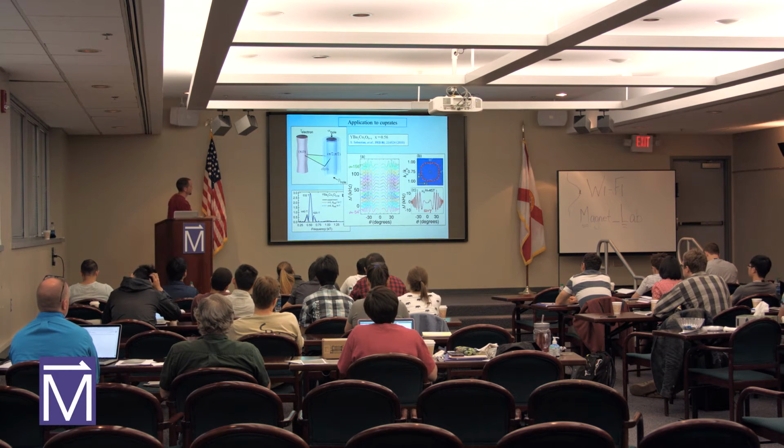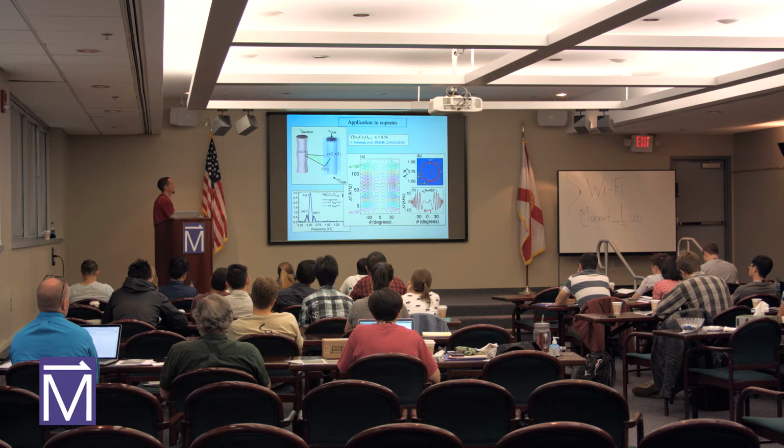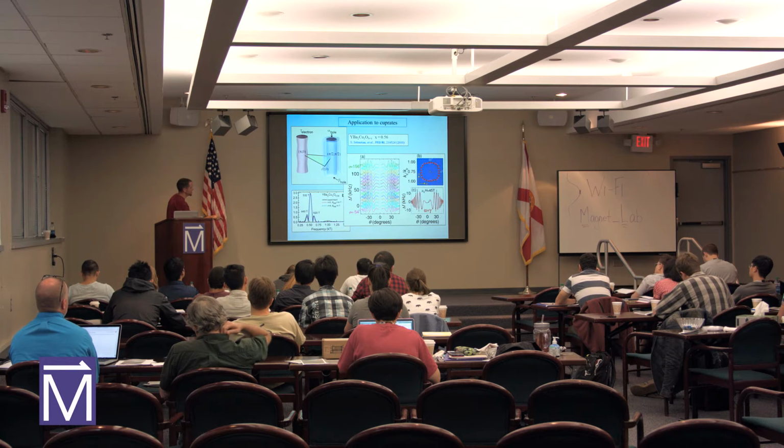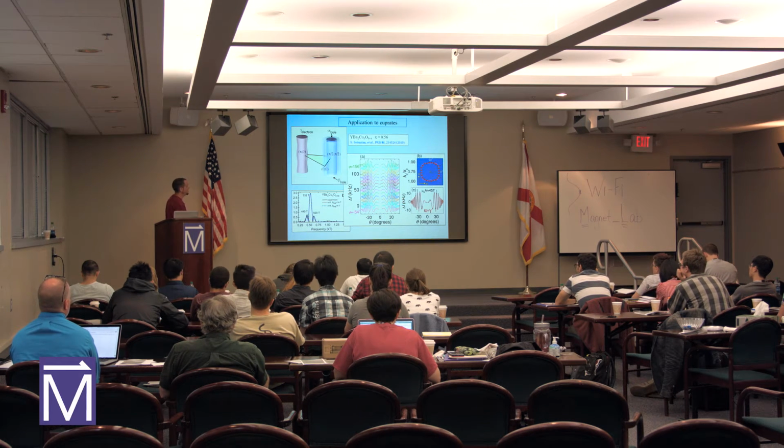So they know there are three distinct frequencies from their fast Fourier transform, but they wanted to know more about the shape of the Fermi surface. So they took this sample and put it into one of these TDO coils, and they continuously rotated the sample in 45 Tesla in the hybrid. Each of these different colored angle sweeps is at 45 Tesla, and after each angle sweep they adjusted the phi angle in spherical coordinates a little bit and did another angle sweep, again and again, and got a complete set of this AMRO data.